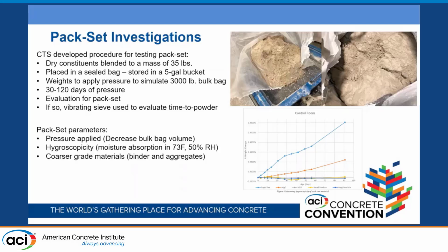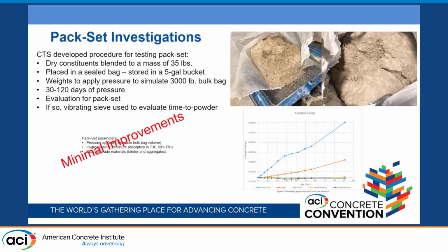So that's the test. And then the parameters they changed were the pressure applied, the hygroscopicity. I probably butchered that, but it's a difficult way to say how much moisture it absorbs in these conditions, 73F, 50% humidity. And then also they looked at coarser grade materials, like a coarser grade of mag oxide or a coarser grade of the phosphate salt. But they got minimal results out of it. They saw no difference after varying all those parameters.